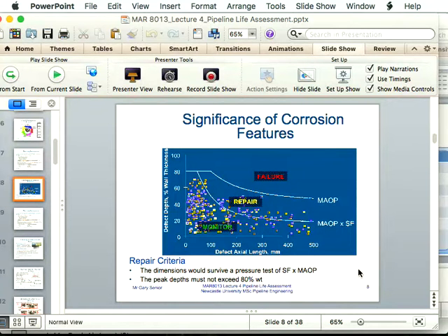Now, even if from an integrity point of view you could justify defects deeper than that, and you could, if the defect was quite short, then you could have quite deep defects. If you have maybe just a 5 millimeter long defect, that could be 90% deep and it still wouldn't fail. But the 80% is a judgment cut-off that ASME have made to say, regardless of what you say from a fitness for purpose view, you shouldn't be having defects deeper than 80%. I think that's a reasonably good rule, because normally operators would be repairing defects long before 80% anyway, once you get beyond 50% if you like.